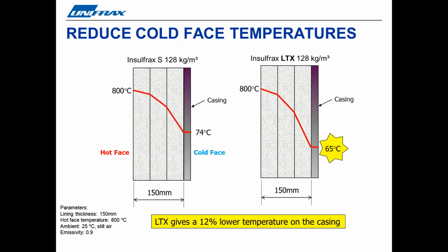This 20% improvement in performance also means reduced temperatures on cold face surfaces. The examples here show how Insulfrax LTX can reduce cold face temperatures by 12% compared with Insulfrax S. Again, this is a typical layered lining system where the thickness and density of the insulation is the same in the two thermal profiles shown.